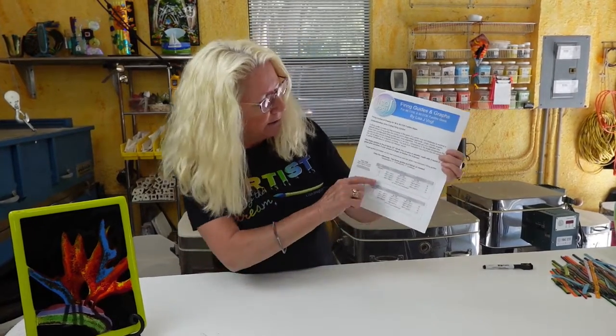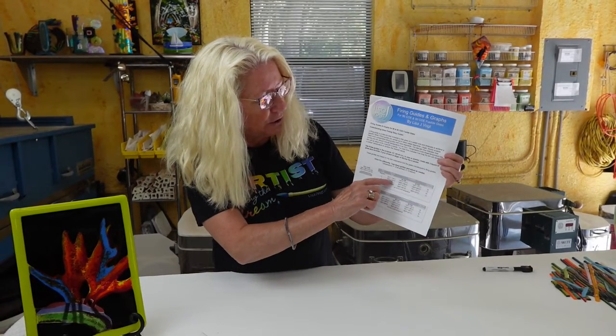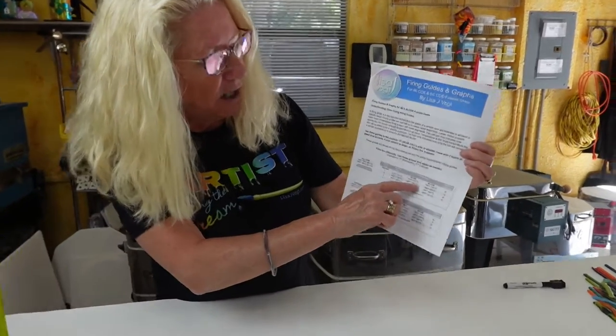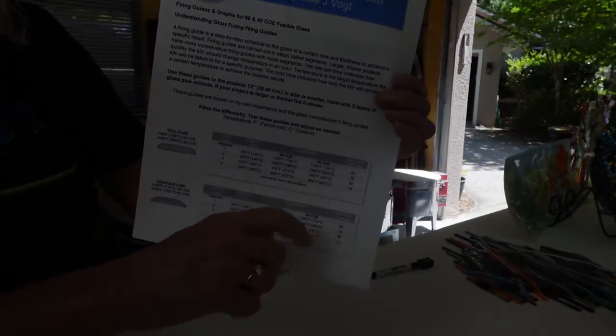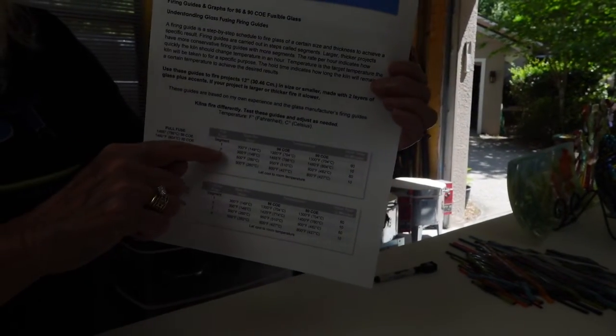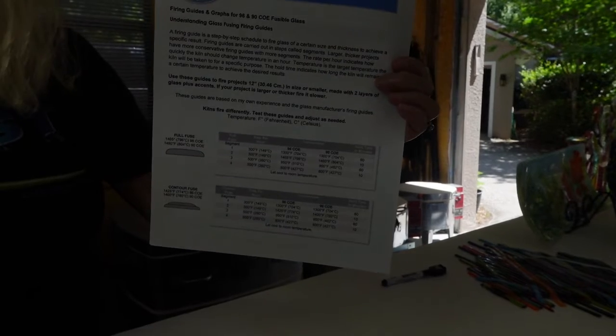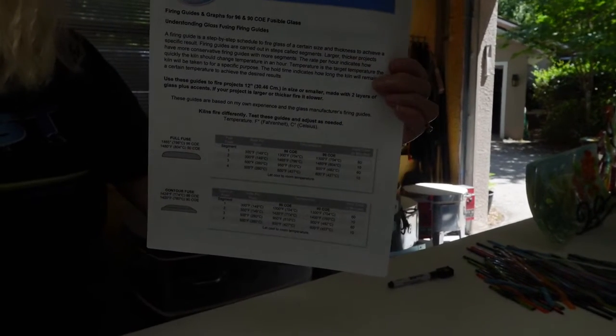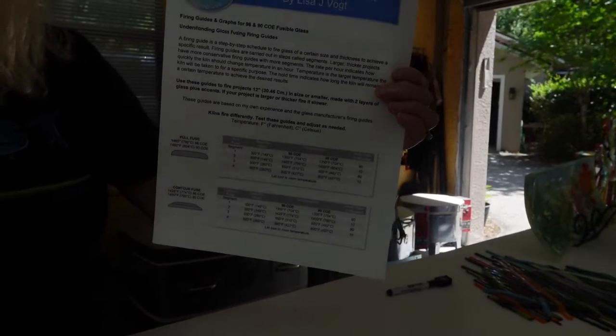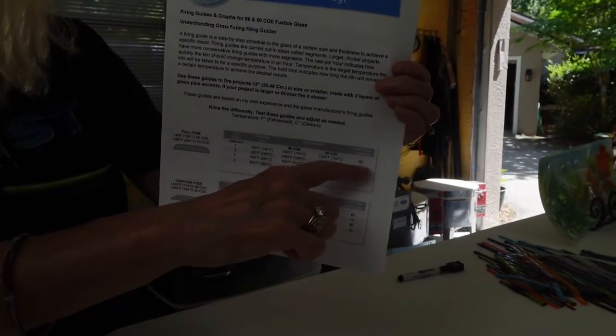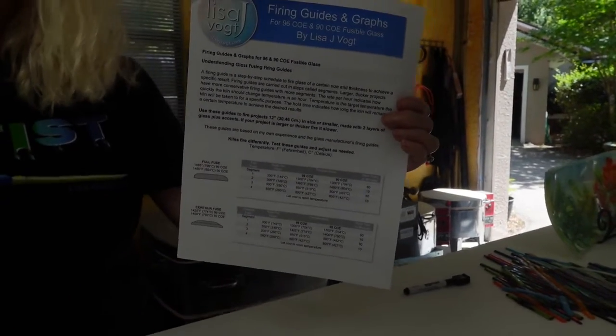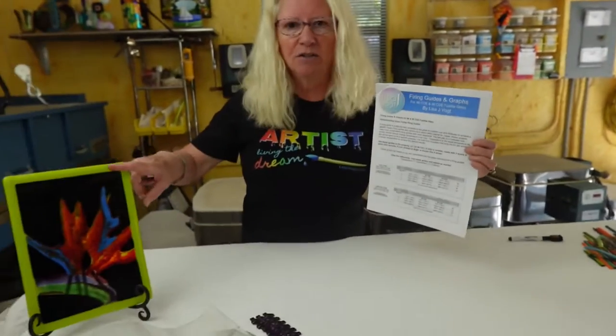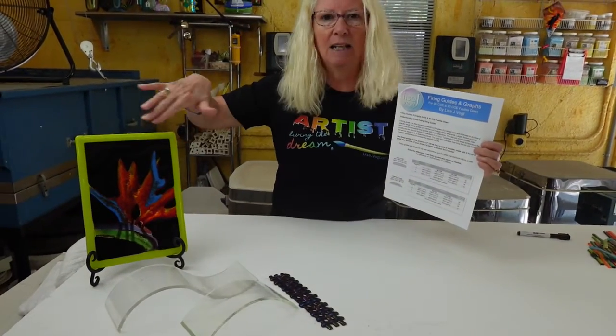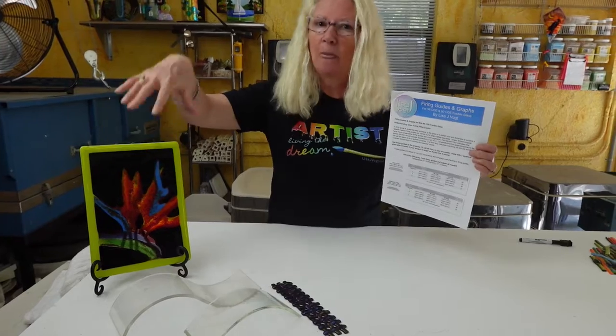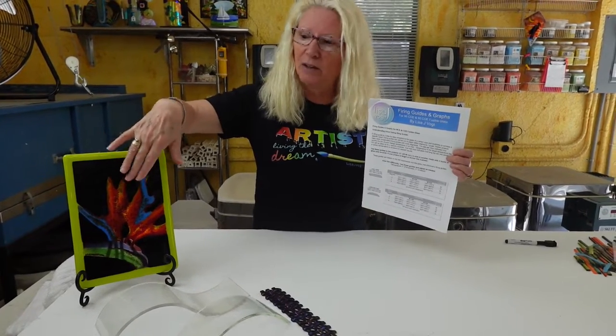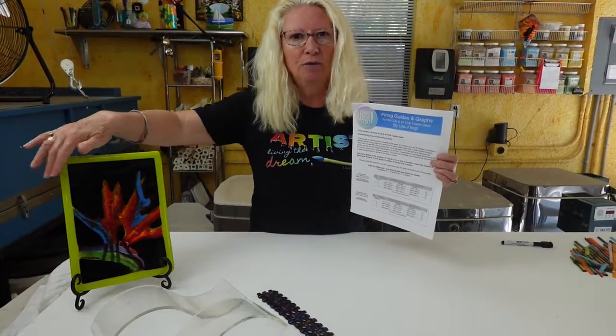Then segment number 2, we go at 300 degrees an hour, either to 1465 or 1480, and we hold there for 10 minutes. Now this segment number 2 is actually our target temperature for this program, or our process temperature, whichever term you'd like to use. And at this temperature, the hold for 10 minutes, we will get the desired result. And in this case, the desired result is a full fuse, something like this, where it's completely smooth. All your design elements are melted together. You have a smooth surface and beautiful rounded edges.